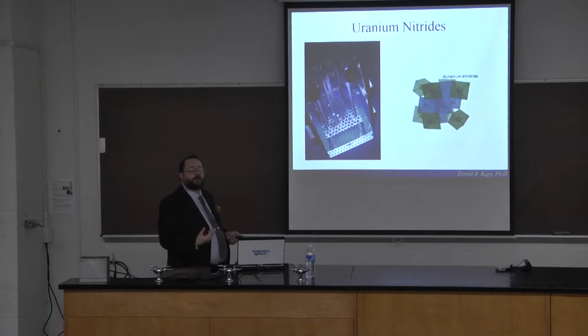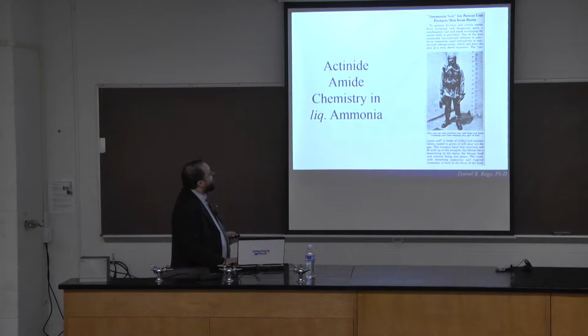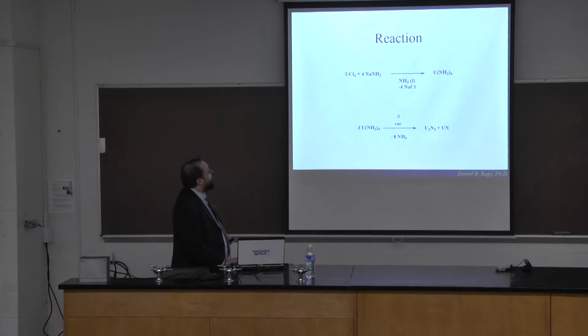So uranium nitride is being considered as a possible alternate nuclear fuel for nuclear reactors to the currently used uranium oxide. And usually this has to be done by a very high temperature route, but I decided to try to do this in liquid ammonia, which at room temperature is a gas, and you need to cool it to like minus 50, minus 60 degrees Celsius. And usually I've done this in a dry ice acetone bath.